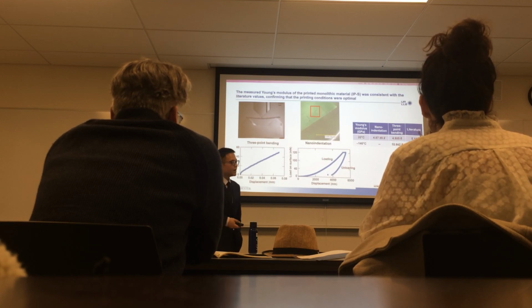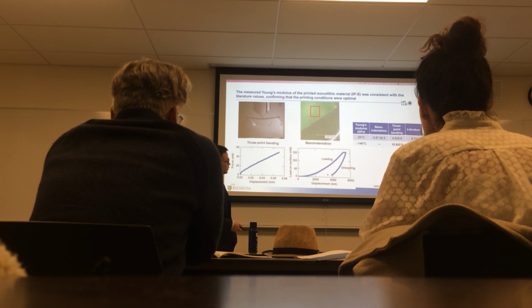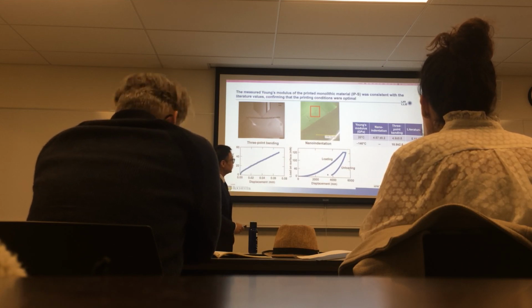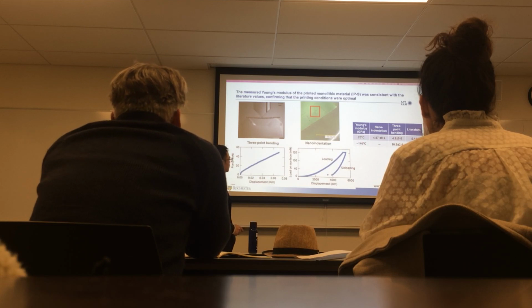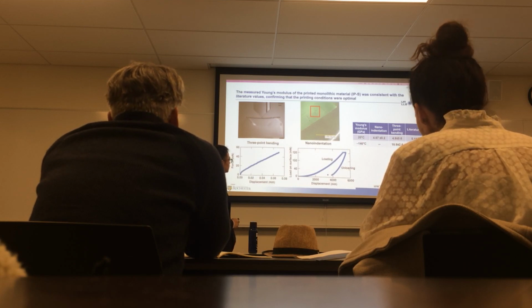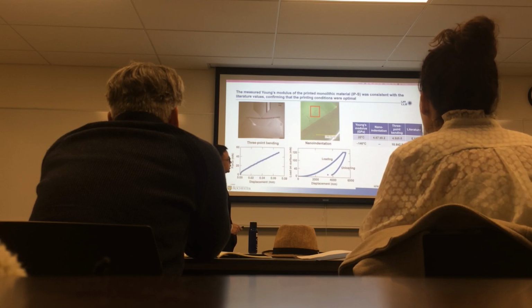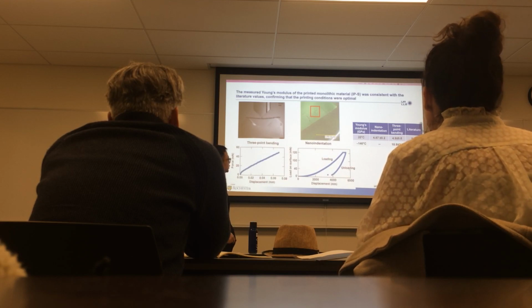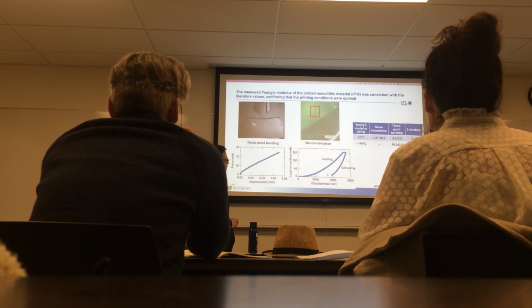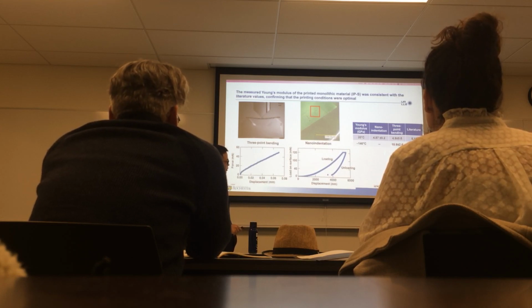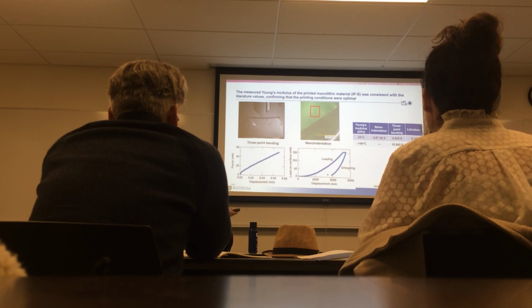The reason we want to compare the measured material properties to the literature values is that we want to make sure our print setup is correct and the resin is fully polymerized. Another reason is that we don't have literature values at cryogenic temperatures, so I used the three-point bending test to measure the Young's modulus at cryogenic temperatures. All these values will be used to calculate the foam structure and also in the simulation.